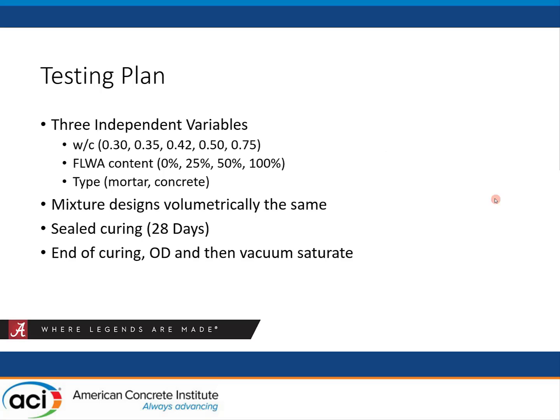So I developed a testing plan where we're looking at various water cement ratios, different saturated fine lightweight content percentages, and both mortar and concrete mixtures. And when we do the design, all the designs remain volumetrically the same so that we can evaluate the effect more consistently. And we were looking at sealed curing to see, if we have a representative structure, what are we looking at?